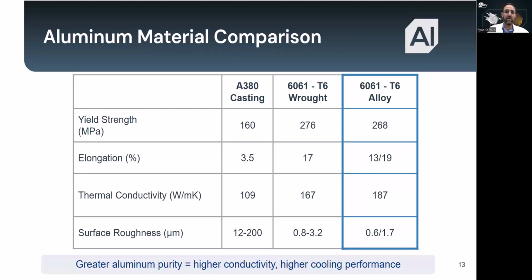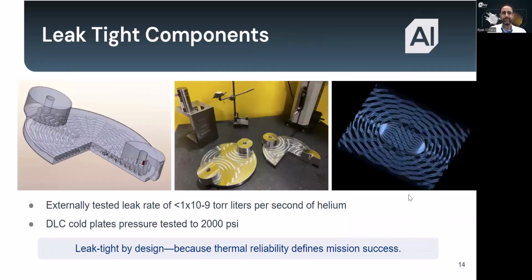We also deliver very fine surface roughness, in this case 0.6 to 1.7 microns, often smoother than wrought, which means we get excellent thermal interfaces right out of the fabrication process without heavy secondary machining, unlike other manufacturing processes. It's very unusual that we have to do any other chemical processing or whatnot to smooth things out. So the takeaway here is simple. We match wrought mechanical performance, but surpass in the property that matters most for cooling, and that's thermal conductivity. Go to the next slide, please.